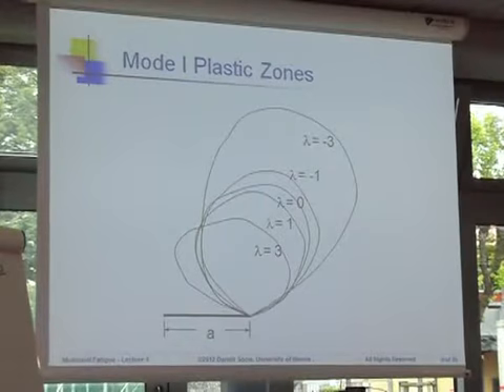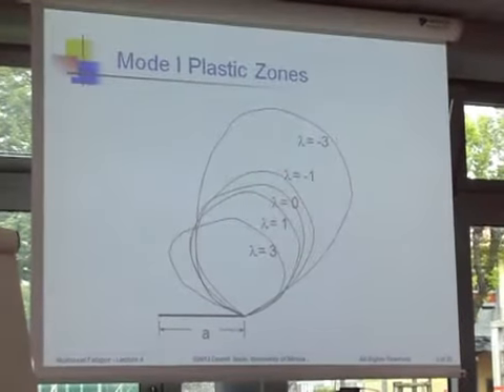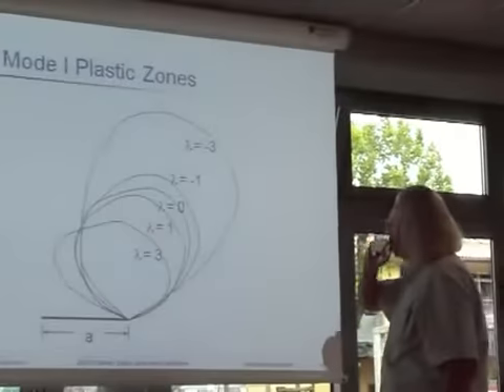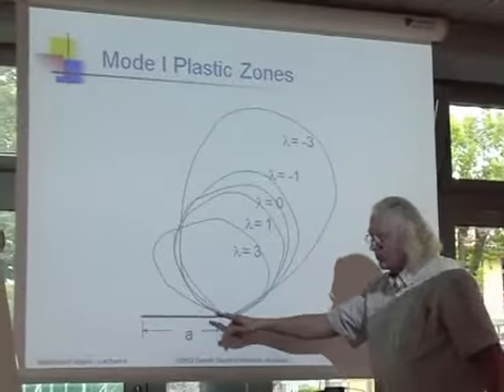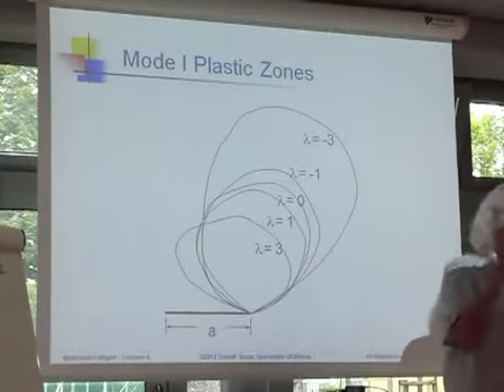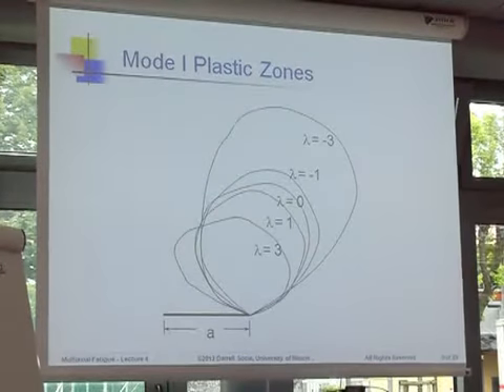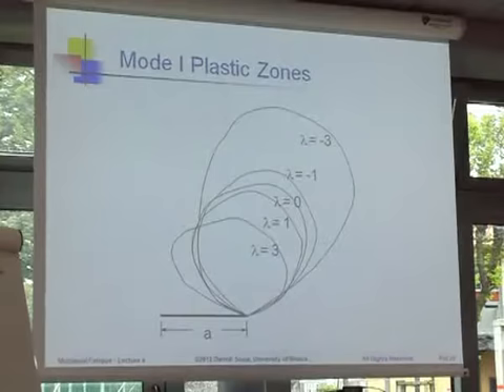Because maybe we have a notion that the plastic zone size should be related to how fast a crack can grow. And that if we have small plastic zone sizes, then the crack will grow slowly. And if plastic zone size is very big, then the crack should grow much faster. And so you can see what happens is the growth of a mode 1 crack. So a mode 1 crack can grow in shear loading. What do I mean by that?